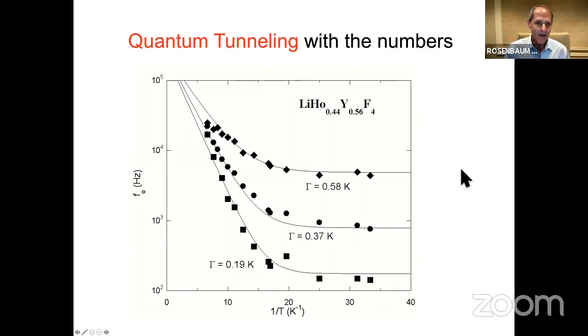So this is this F0, the most weakly pinned domain wall. And I'm looking at it as a function of 1 over T. So on the left here, towards 0 is high temperature. To the right is low temperature. Obviously, I'm picking log F0 versus 1 over T, because in the classical limit here, I expect Arrhenius behavior, which is a straight line. And now what I can do is look at a series of different transverse fields. Remember, I have a quantum parameter now.